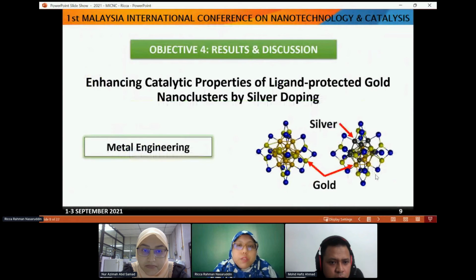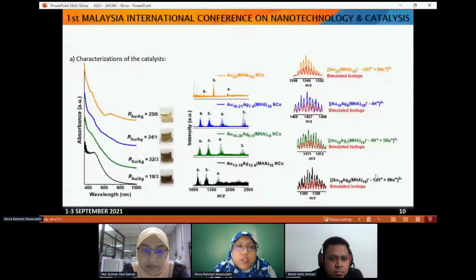So for the results, these are the characterizations of the catalyst. If you look here carefully, this is only gold. So you will have the characteristic peaks of this gold 25 nanocluster. You have a peak at 670 nanometer. You also have a peak here at 450 nanometer. So this is gold 25.